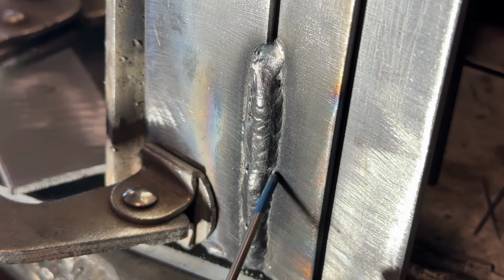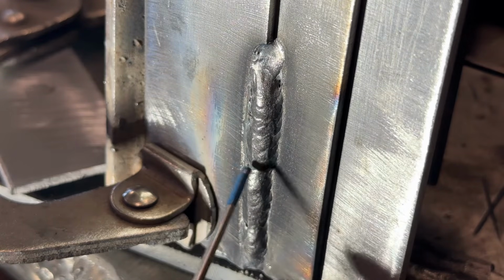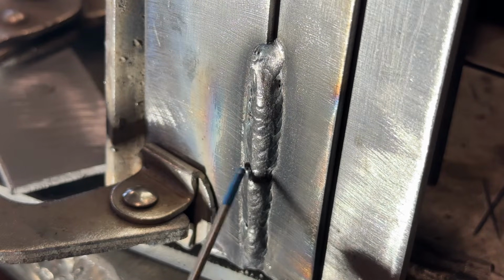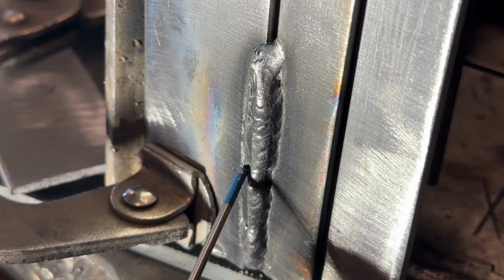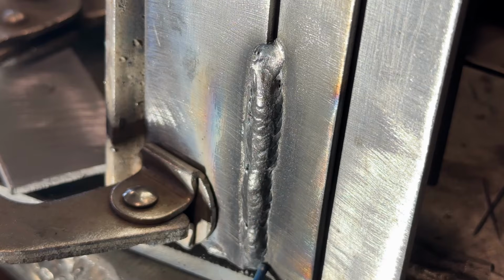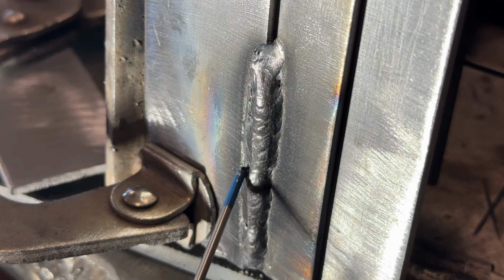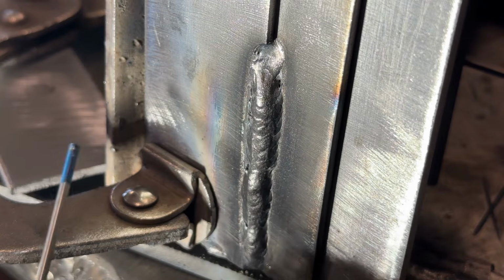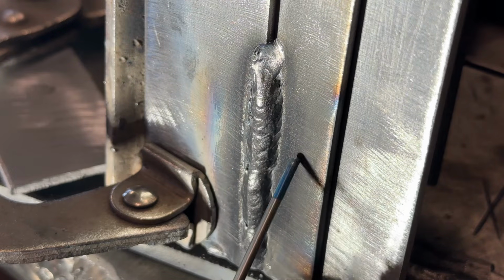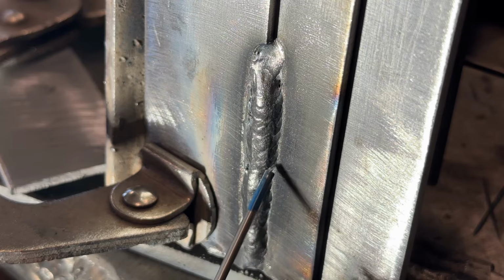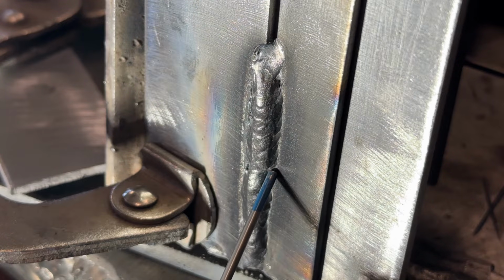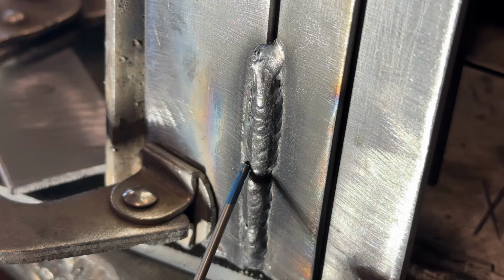So we have a couple choices that we could make right now. If we add up all of the details here like it's a game of Clue, all of the clues, we can deduce, okay, a little bit of porosity, very minor, a little bit cold. Well, we can either lower our wire feed speed a pinch to match our voltage a little bit, so our heat to metal ratio will remove some of the metal, or we can bump up the heat.